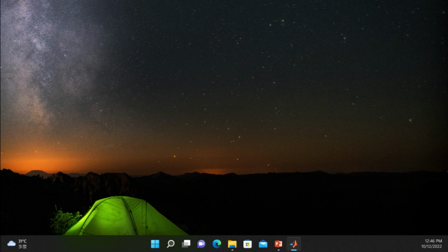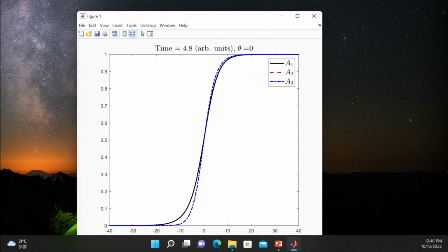What happened in the very beginning? You see the profile changing because it is trying to minimize the energy. Initially, I was setting all 3 amplitudes to have the same profile. Very quickly, you will see they spread out. But you will see, oh no, I only see 2, right? You only see 2 colors. You don't see A2. So what is happening here is that my interface normal is in the x direction, and K1 is also in this direction. So the inner product of K and the interface normal will be 1. So that's why you are showing A1. It is merged. That's right.